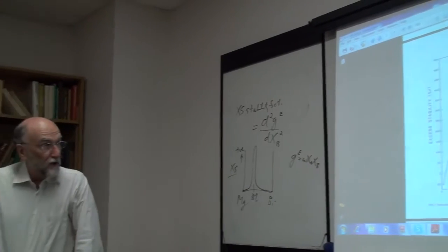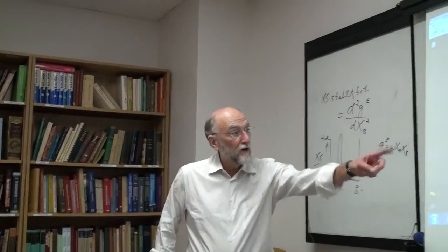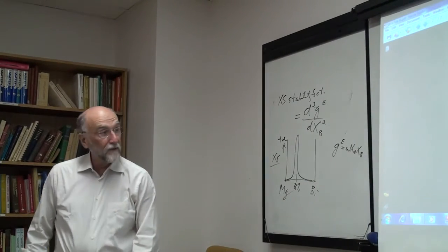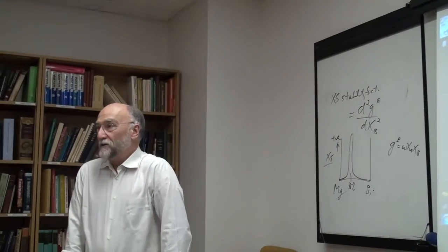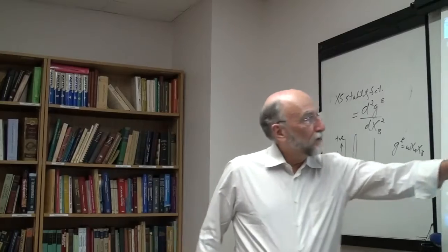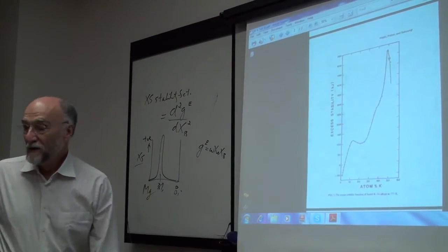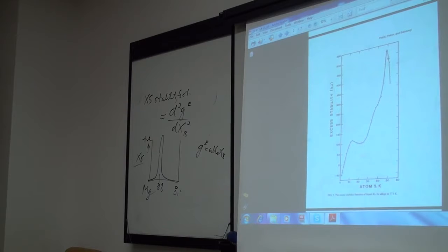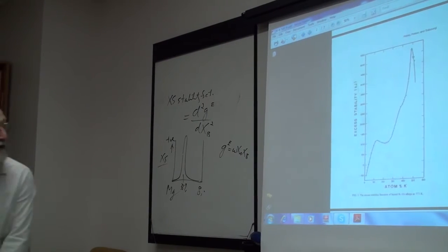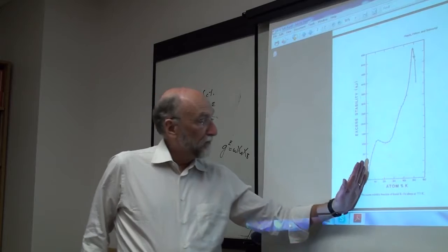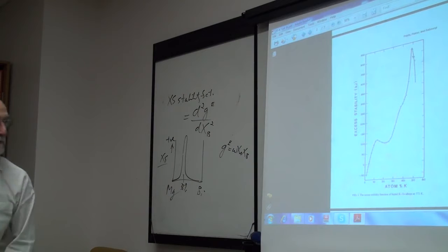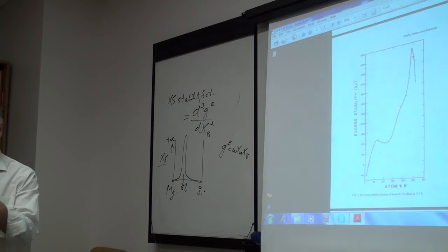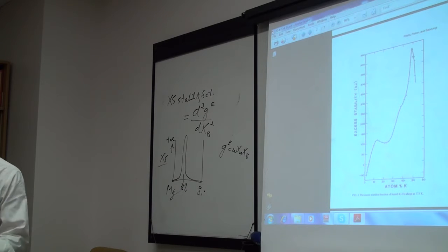So potassium is very metallic, tellurium is basically a semi-metal, and this is the excess stability function. And isn't it interesting, you have two peaks in the excess stability function, and possibly even a tendency towards a third peak here. This would indicate that you have in fact two compositions of short-range ordering. This is completely miscible. You go from potassium to tellurium, but around 50% potassium, you have a very strong short-range ordering, with potassium and tellurium in a 1-to-1 ratio.